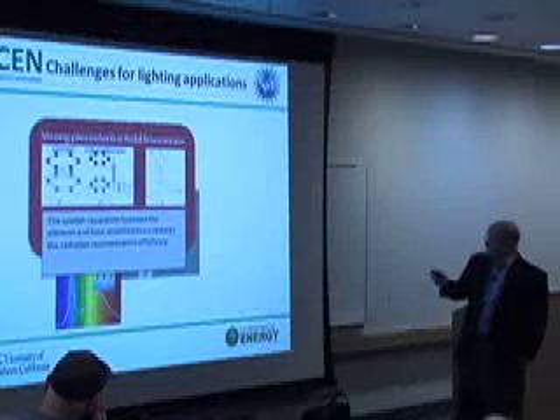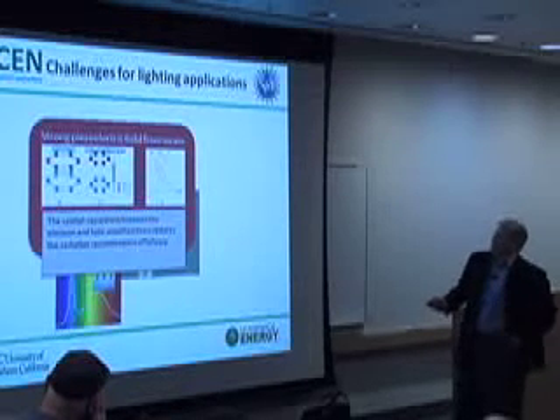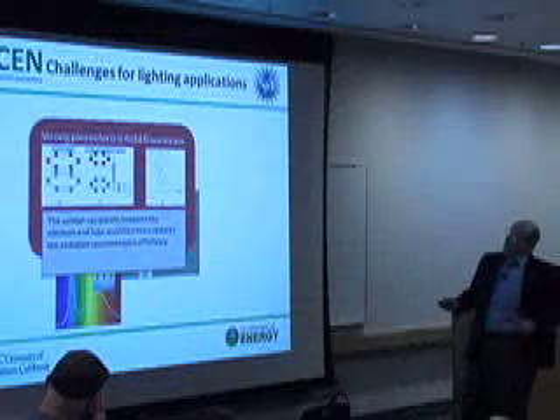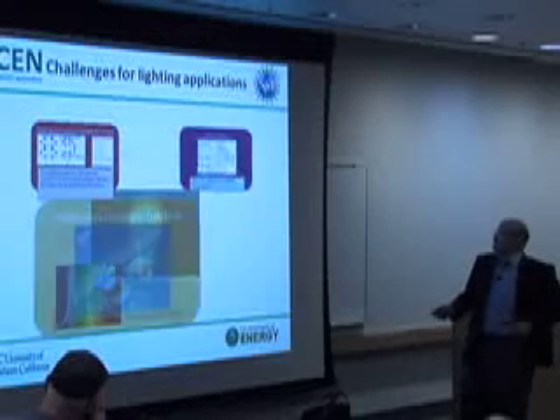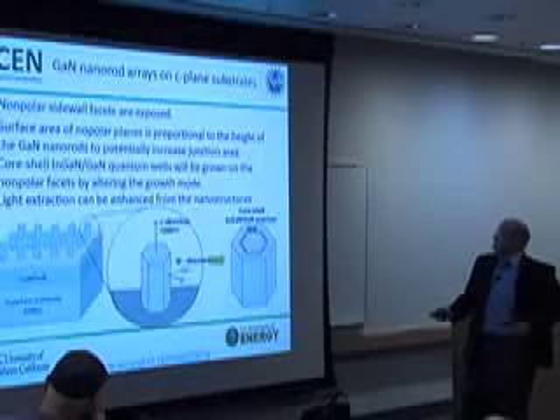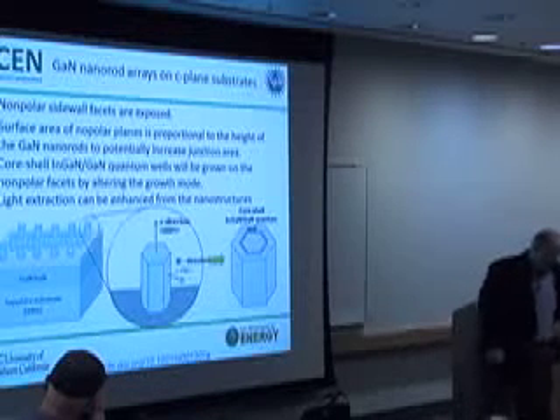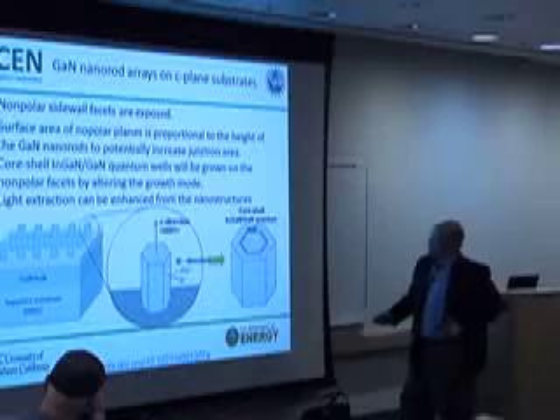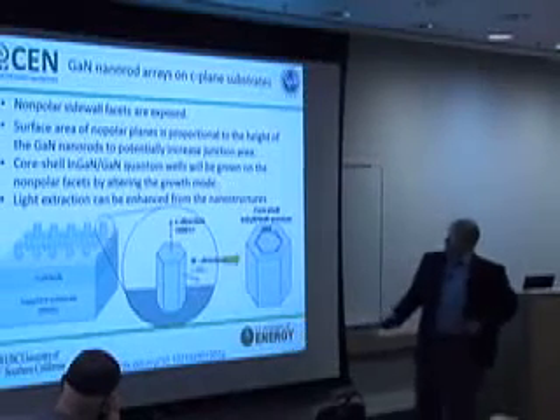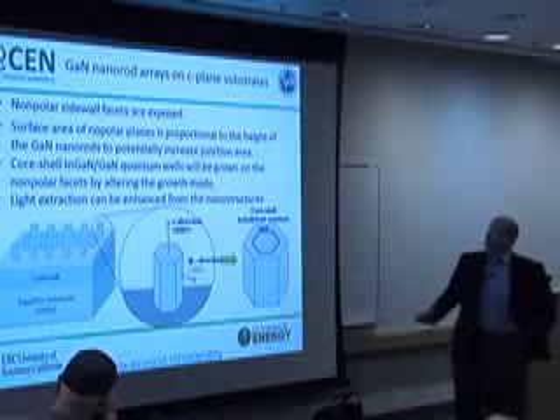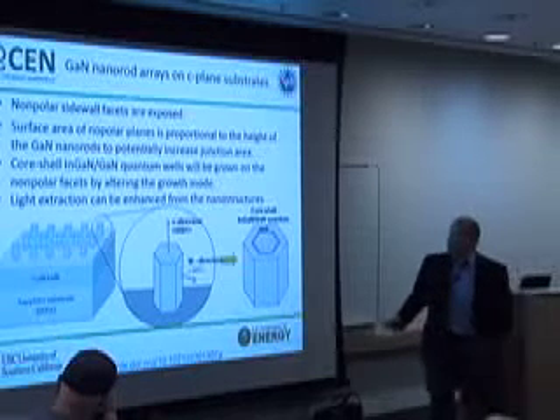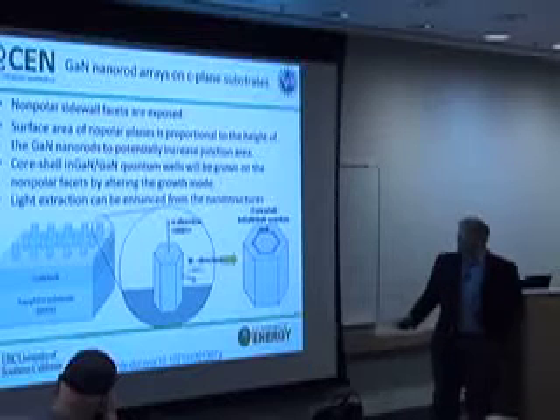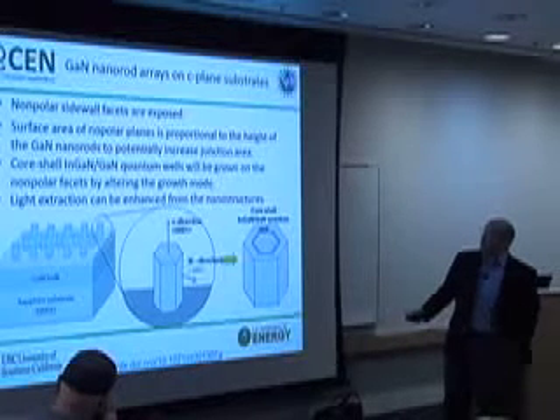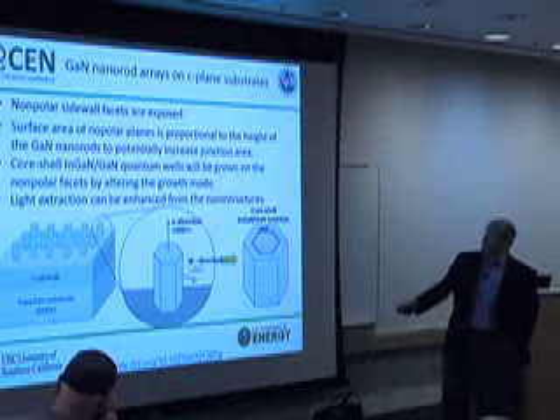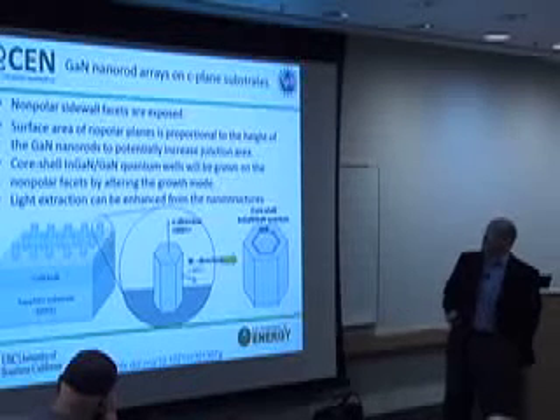And so we wanted to explore, like is a big effort here at UCSB, the growth on nonpolar substrates. So let me skip ahead. This is all PR. So what we're doing is to use C-plane sapphire, grow bulk gallium nitride on it, form a pattern on the structure, and then grow nanorods perpendicular to the substrate. And these nanorods naturally form with 1 1 bar 0 0 surfaces, namely M-plane surfaces around the perimeter.